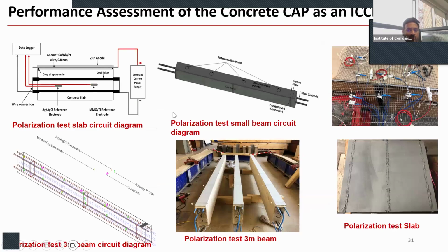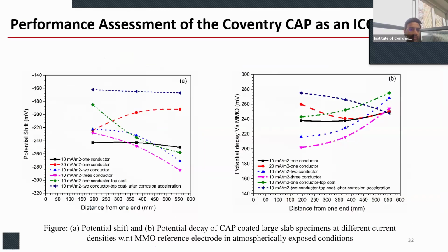We tested it for various anode steel geometries, starting from small slabs, then a half meter beam, then a 3 meter beam, then a full 1 by 1 meter slab with various steel concrete densities, to figure out how much protection current density it can sustain, and what spacing of the primary and neutral conductor is required. It's been tested for about 4 to 5 years in the laboratory before finalizing this anode.